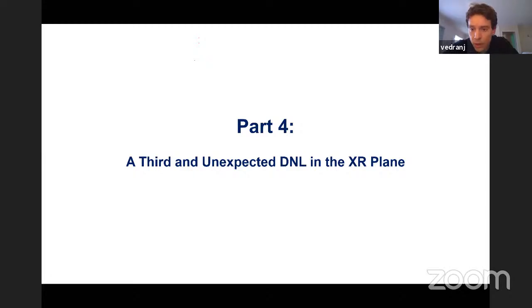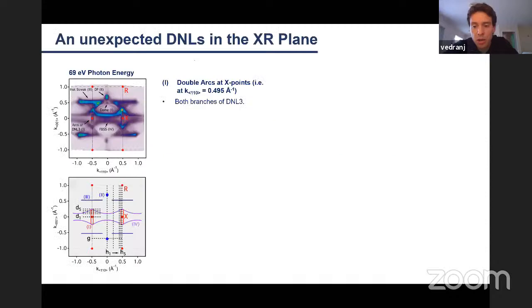So this panel A is the cut along 69 eV, and the photon energy is essentially probing the kz along the 110 plane, containing both the X and R points, which I show you in the top left here. And once again, we have a little schematic which summarizes for us the main features, and we can quickly summarize these before we delve deeper into them.